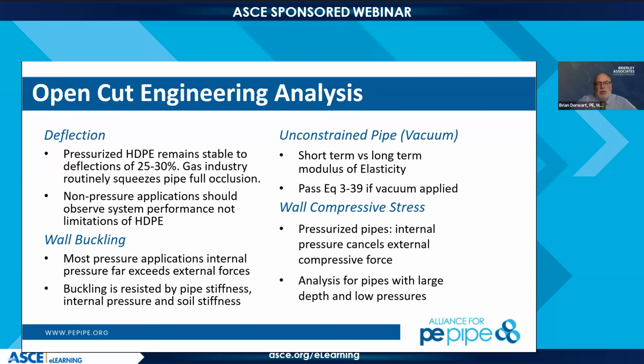The thing that the trench fill brings to the table, though, is it's usually a granular material, which means that the deflection of your pipe, the ovalization, is going to occur usually just during construction. And once the soil has settled on the pipe, and it is ovalized a slight amount, the sidewalls of the pipe are now being supported by the soil. That action is not going to continue to progress. You have a single short term, the pipe may be slightly ovalized, and you can pretty much calculate that if you want based on the Iowa formula and what you have for compaction in the trench and looking at the surrounding soil to see whether that trench fill is going to remain stable.